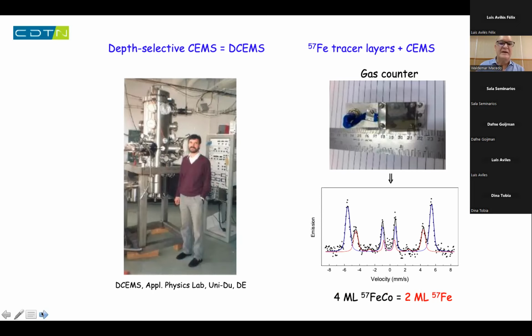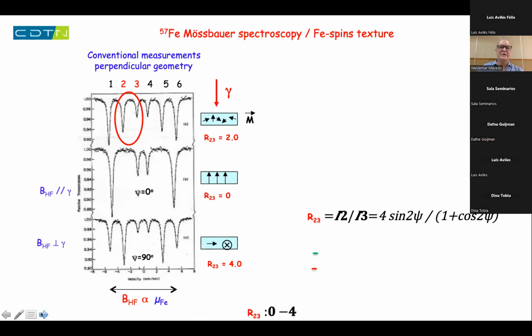And another important thing when you do Mössbauer spectroscopy is that from the line intensity ratio between lines 2 and 3, you can know about the texture of the iron spins, okay? That means this line is for a random distribution. We have lines 2 and 3, the ratio is 2. When the spins are parallel to the gamma rays, line 2 disappears, the ratio is 0. And when the spins are perpendicular to the gamma rays, this ratio is 4.